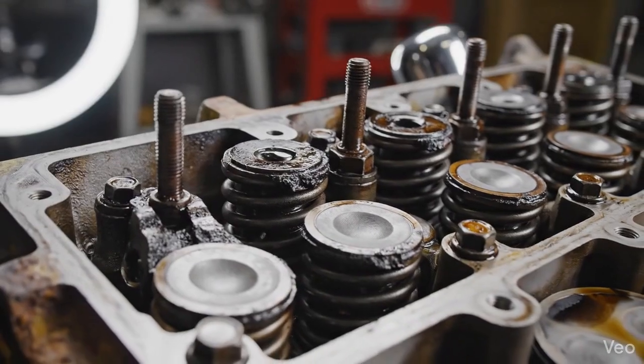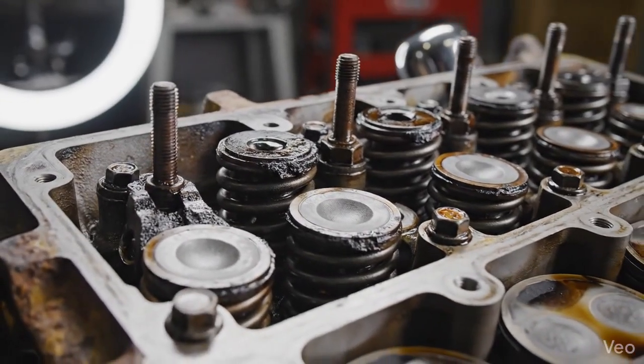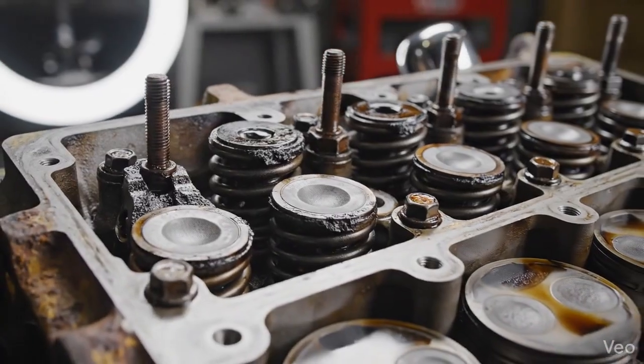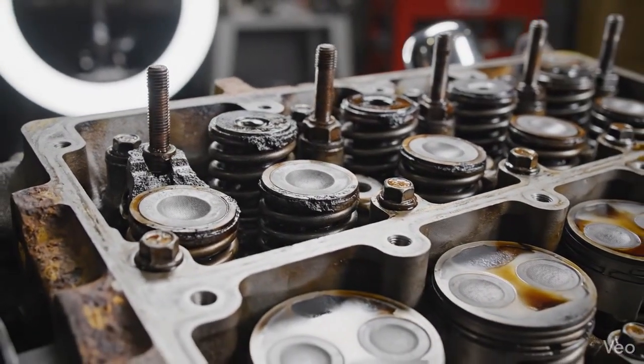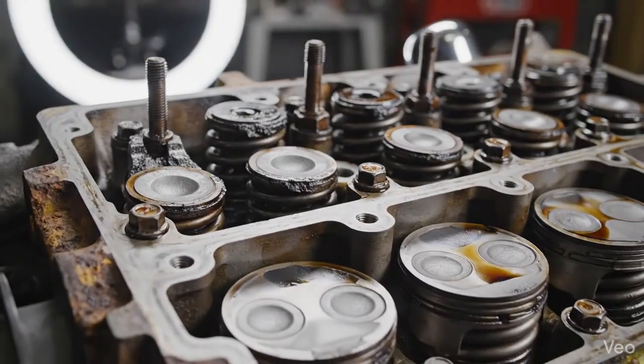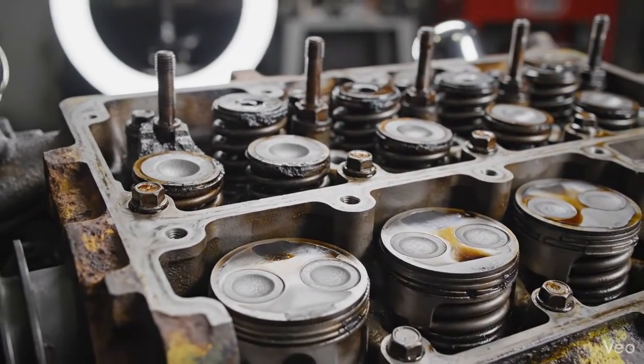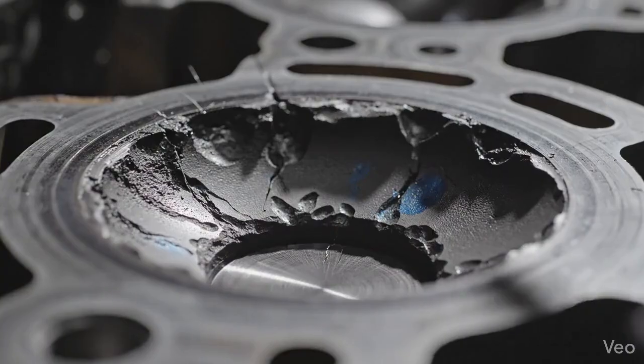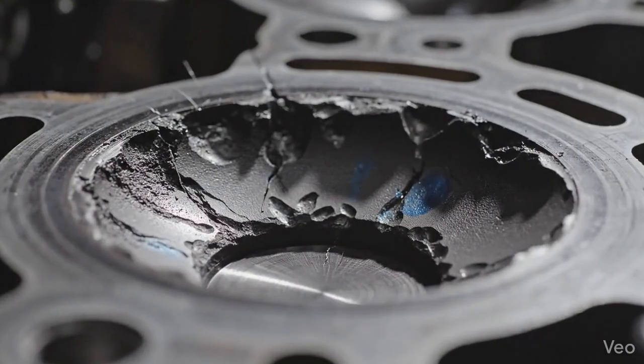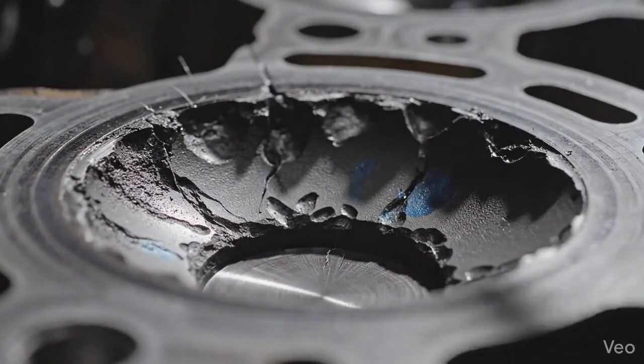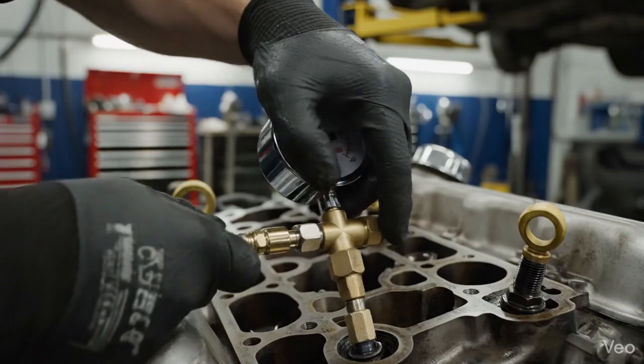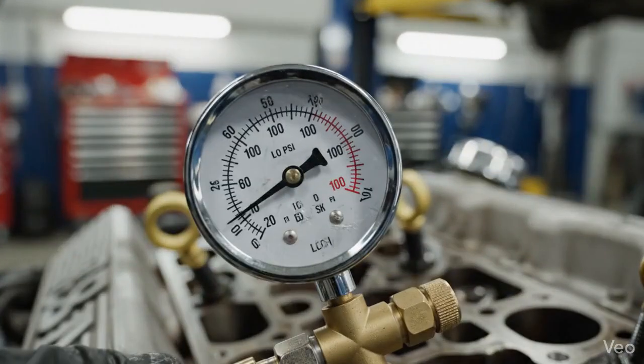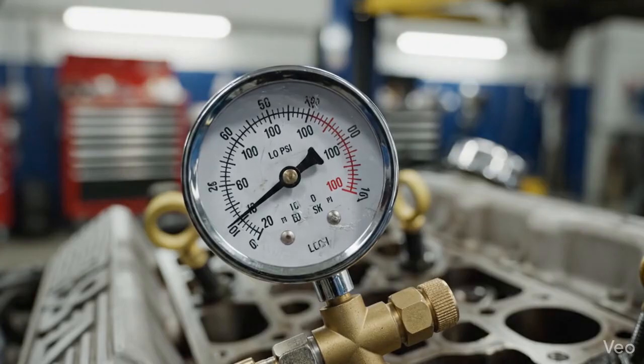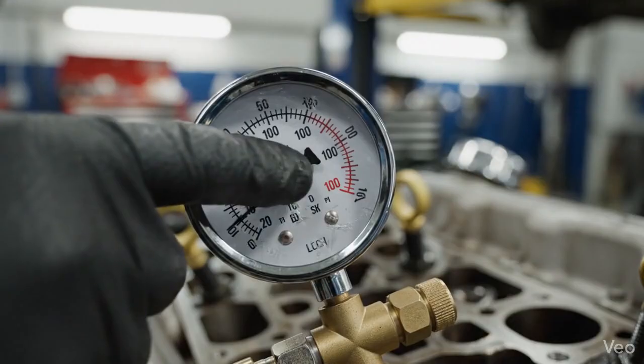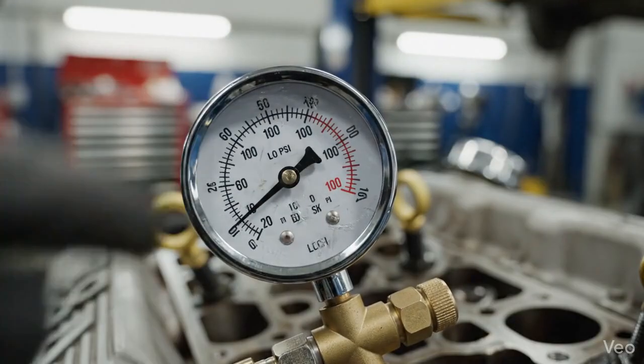On a highway-driven vehicle, with a pre-emissions engine still running its original soft iron seats on modern pump gasoline, measurable recession and compression loss can develop within 20,000 to 30,000 miles. In more severe cases, the valve sinks into the head far enough to lose effective sealing on that cylinder. It presents as a compression loss that gets worse under sustained highway speed, exactly the type of symptom that gets misdiagnosed as a head gasket issue when the real problem is in the seat interface.